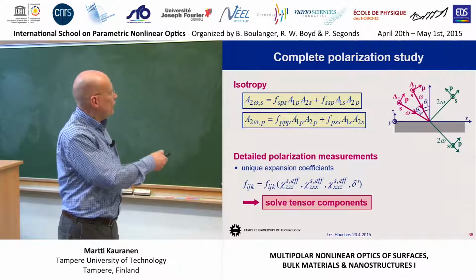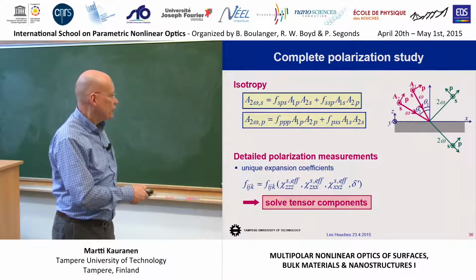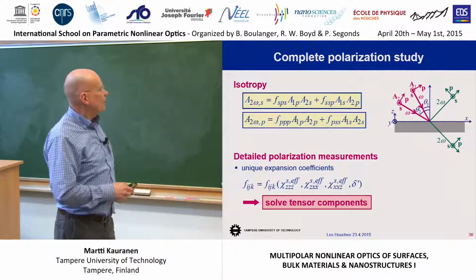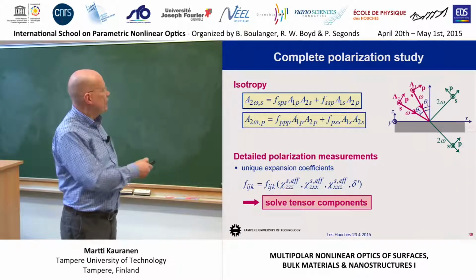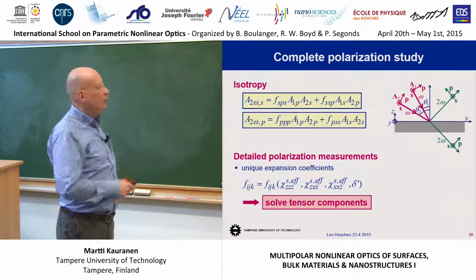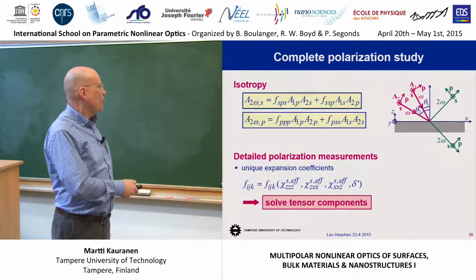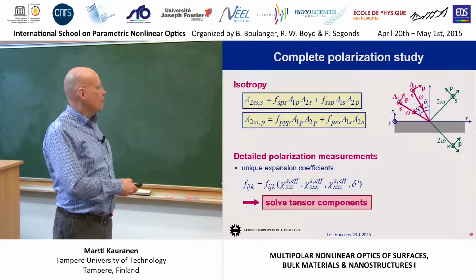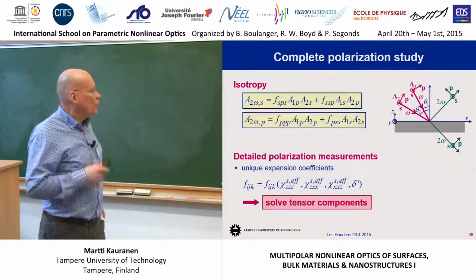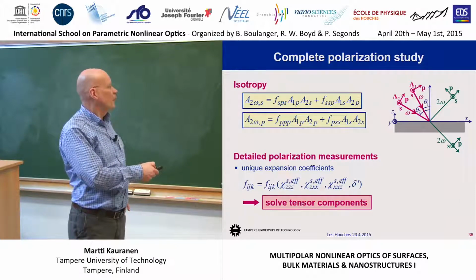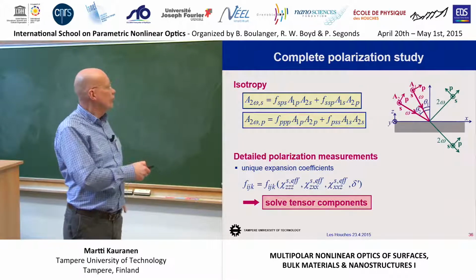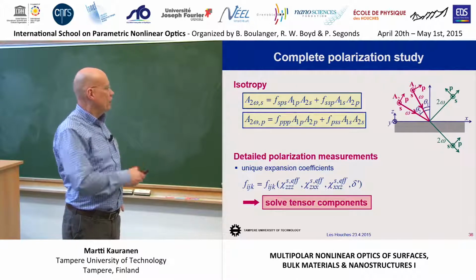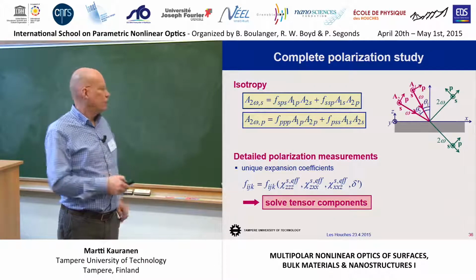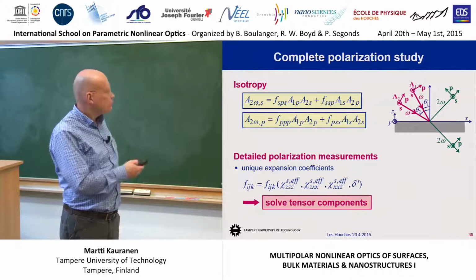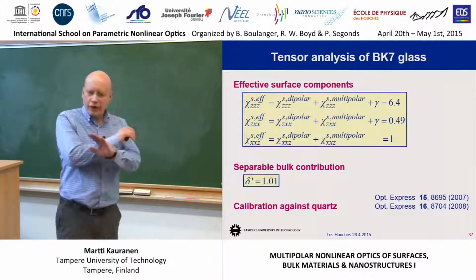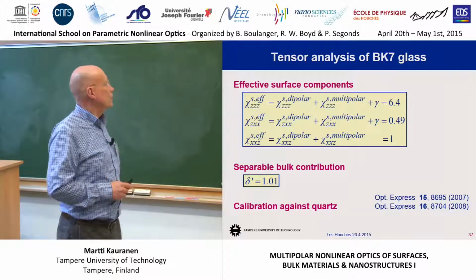And these parameters here, they depend on these tensor components that we are trying to determine. Okay? So basically, if we do enough studies where we somehow relate these F parameters to each other in a reliable way, we can work backwards and in the end solve for these tensor components. So what we have to do is a set of measurements playing with the polarizations of the fields in order to get unique solutions for these F parameters. And once those are known, we have a set of linear equations to solve for the actual tensor components. Okay? And again, to make a long story short, this is what we get.